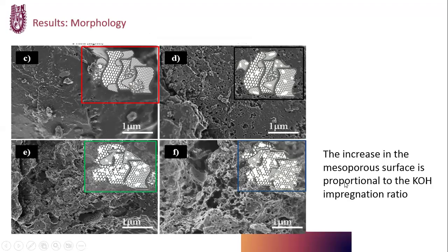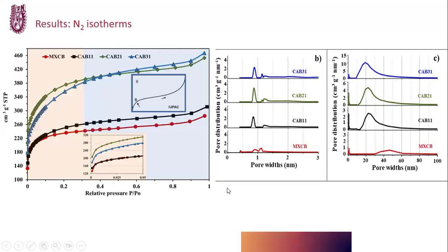The impact of the activation process on the gradual development of the porous structure is observed in some images in this slide. We can observe that the increase in the mesoporous surface is proportional to the potassium hydroxide impregnation ratio. Nitrogen isotherms reveal differences in material textural parameters. In this slide, we can see type 2 isotherm curves, like this one, for all carbons. The initial part of the curves corresponds to the completion of monolayer coverage. The values above 0.3 relative pressure are associated with the multilayer adsorption that takes place in the mesopores.